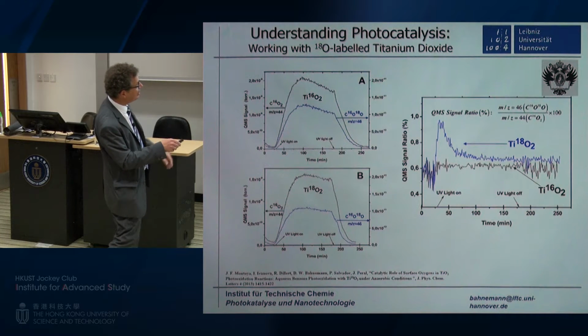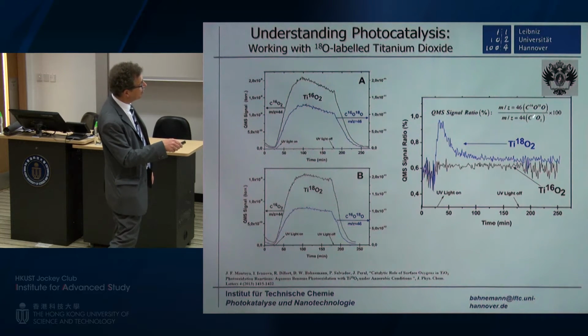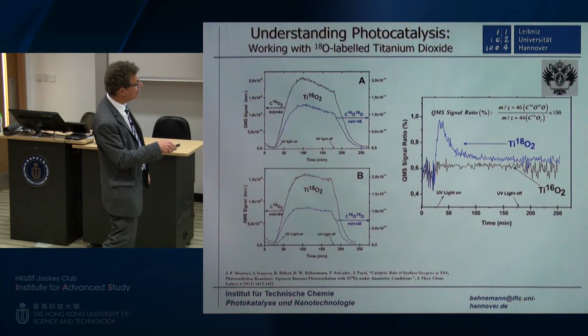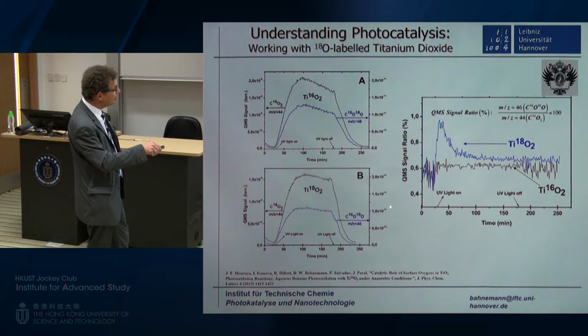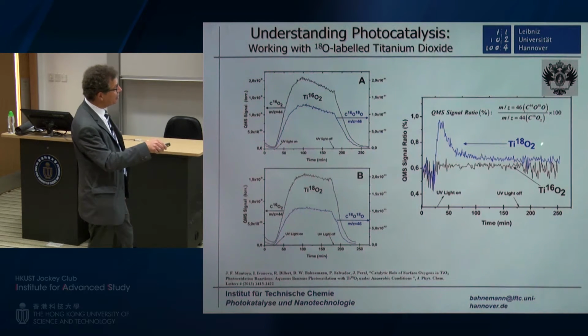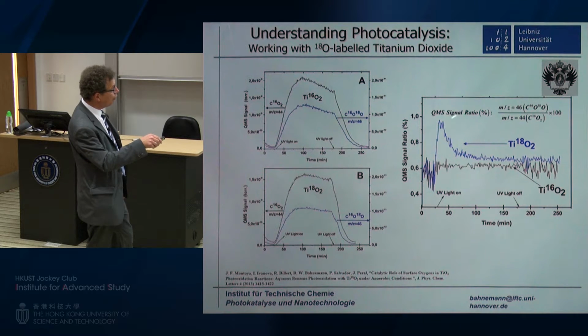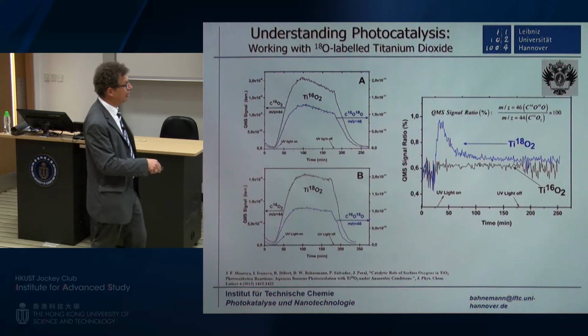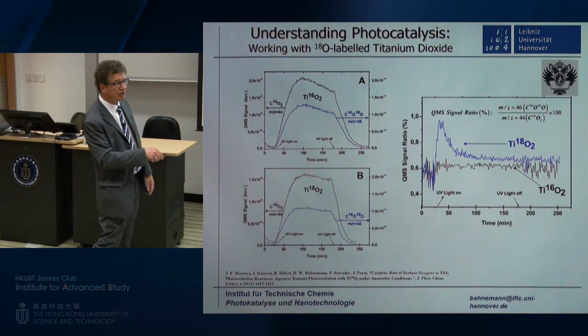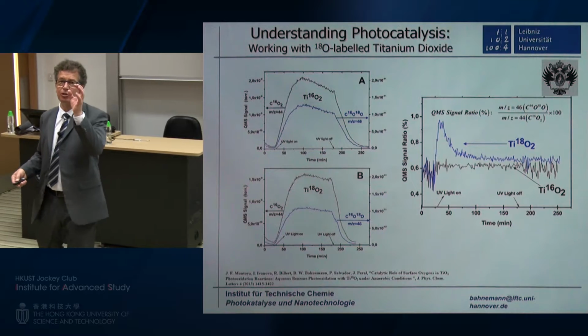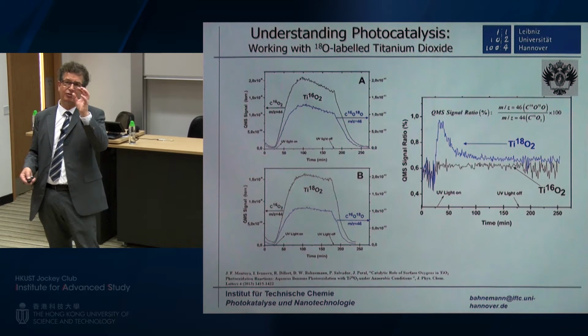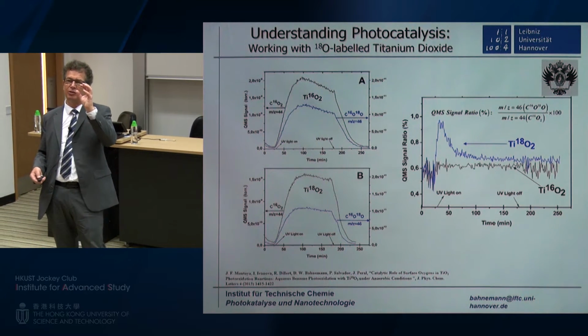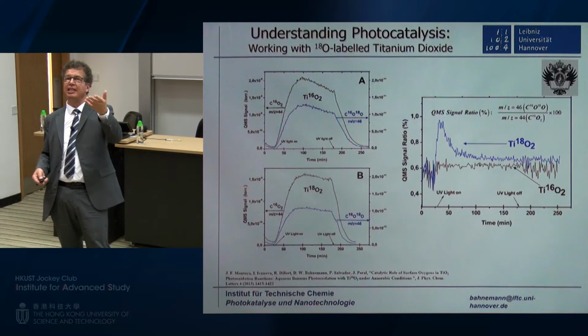So in order to analyze the data, it's better to look at the ratio of the mixed carbon dioxide and the pure carbon dioxide. And if you do this, you find that indeed on the labeled TiO2, initially you form much more of the mixed carbon dioxide. Then they behave the same, but they should behave the same because we are only talking about the top level of our TiO2 where the bond breakage occurs, and then you get a repair.